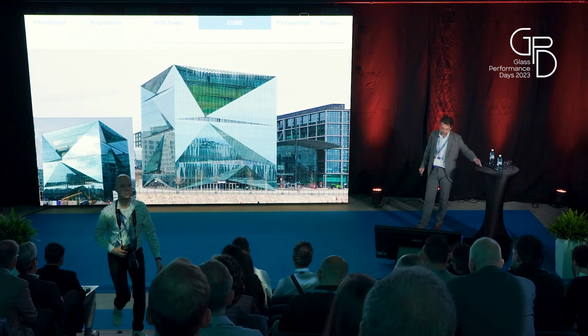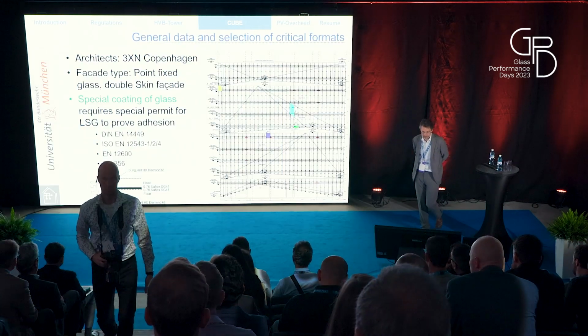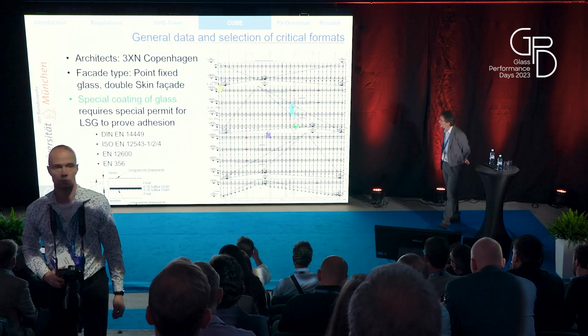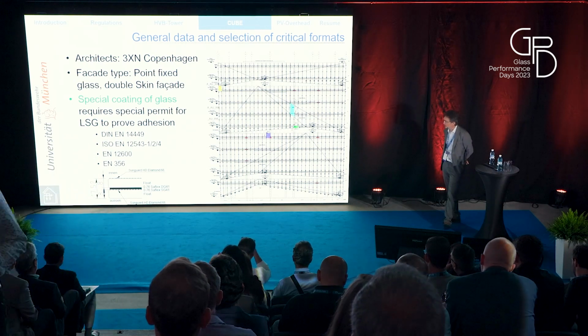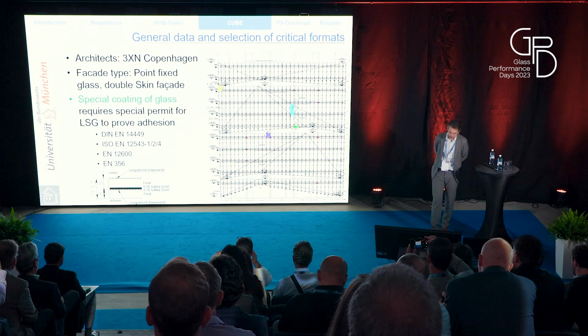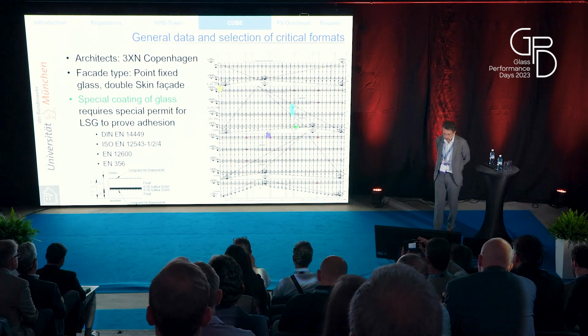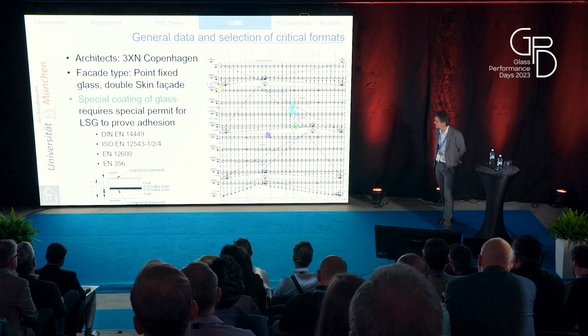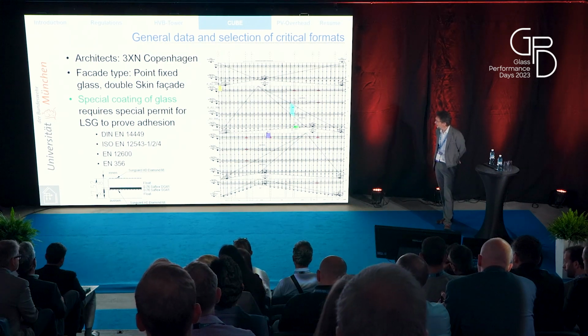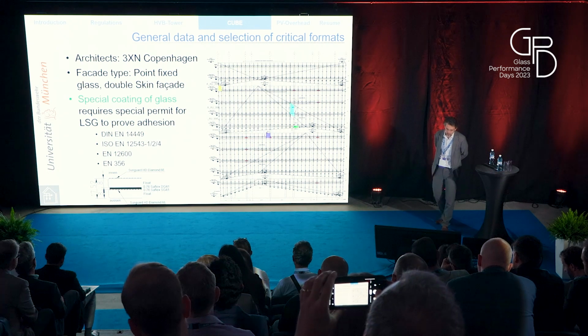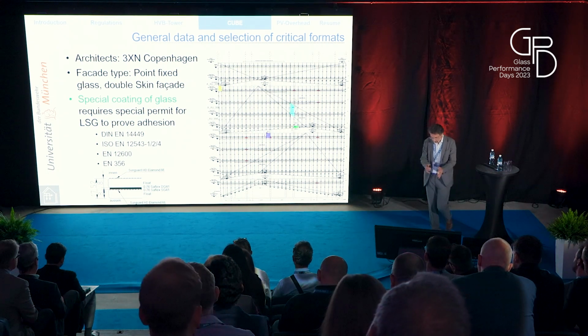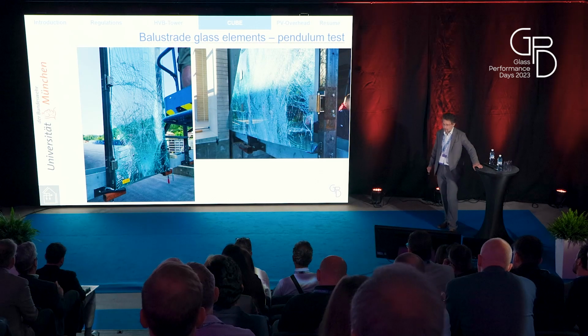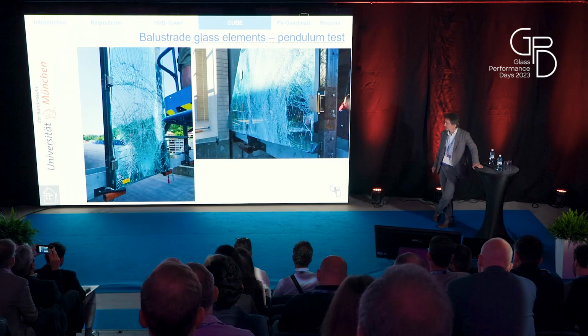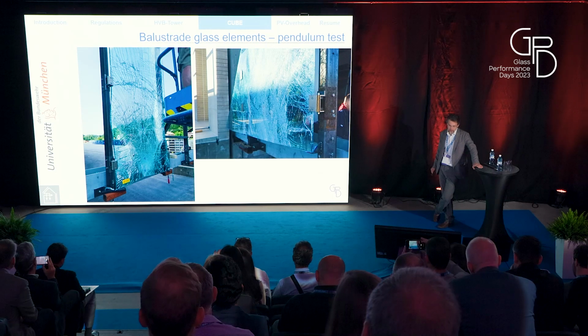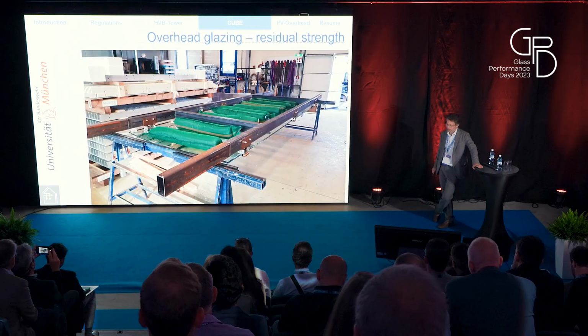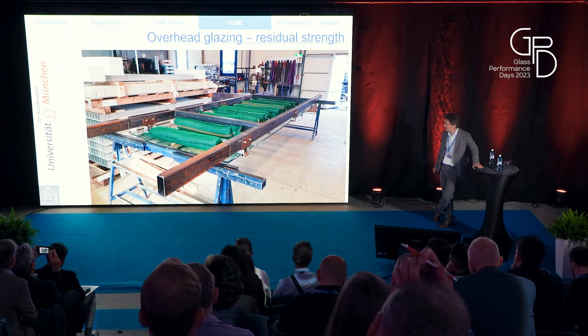The outer facade has point-fixed glazing, and because of this geometry we have a lot of different formats. There was again a special coating of the glass, which requires a special permit for laminated safety glass. Then you look at the sketches, pick out the worst formats, and do the small sample testing and full-size testing for the balustrades, because there are also some balconies in the situation. Also, because of the inclination, overhead glazing tests had to be carried out.